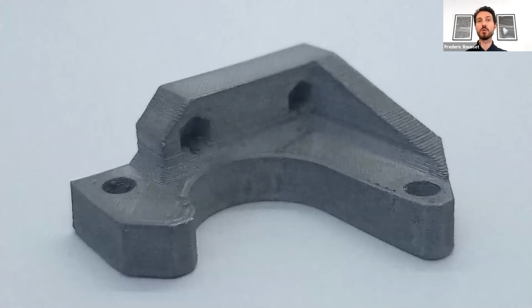The part was done at 0.6 liter per minute at first for the gas flow rate. So we put it at 1 liter per minute, and you can see that the part is now perfect. We don't have any blisters on it. So the solution worked quite well.